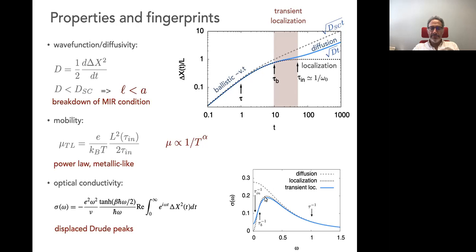In the other two cases, which are transient localization and localization, this Drude peak has shifted to a finite frequency peak. Well, you have depleted this region of low frequencies simply because you have suppressed the DC conductivity or the mobility. And this will be important in the last part of my talk.